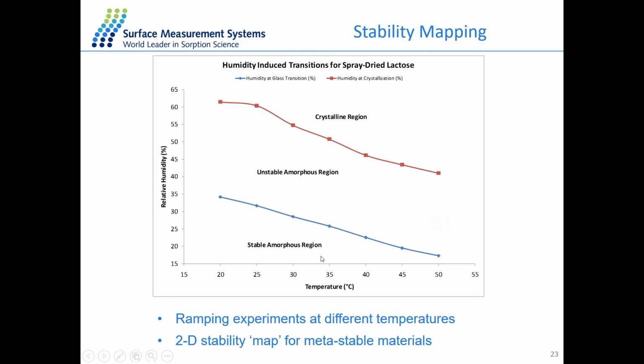And the previous experiment was just at a certain temperature, 25 degrees. And if we do a series of ramping experiments at different temperatures, then we can get the stability mapping of the metastable material. So at each temperature, we can get 2 points, one for the glass transition, the other for the crystallization. So with increasing temperature, we can get a blue line for the glass transition, and then a red line for the crystallization.